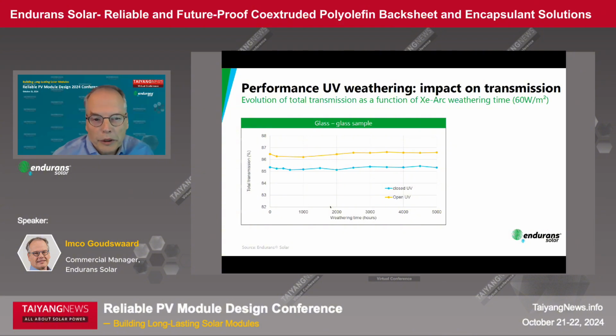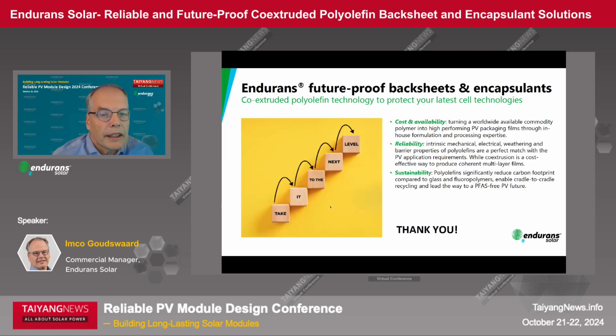Here, of course, for encapsulants, the optical properties are very relevant, and especially stability under continuous UV light, and that's what you see here, up to 5,000 hours UV exposure, where there's no change in transmission. So, which proves it's a very stable product. Next slide. That is the last one.